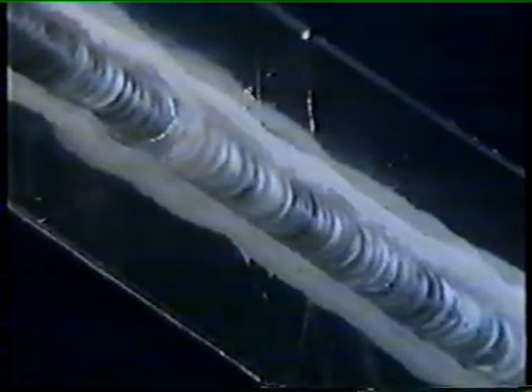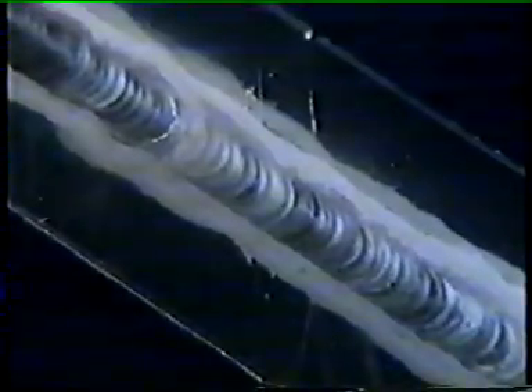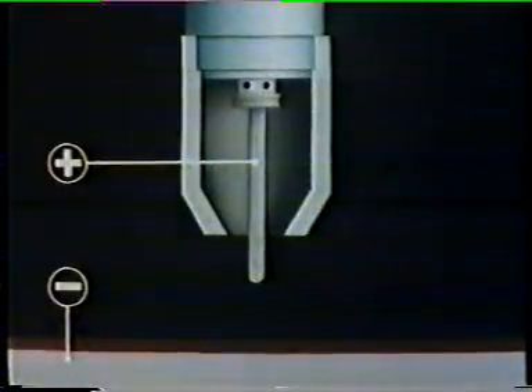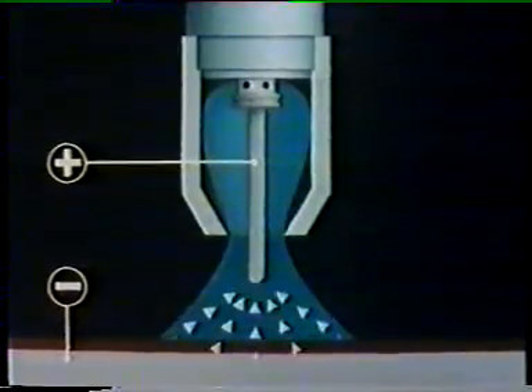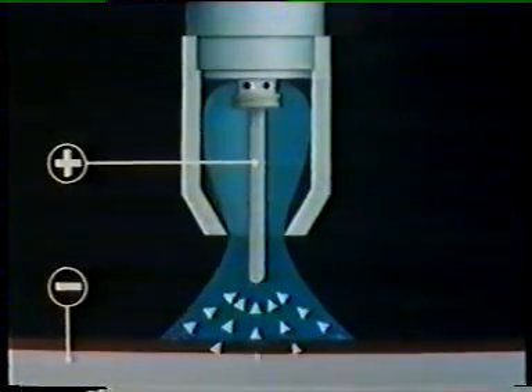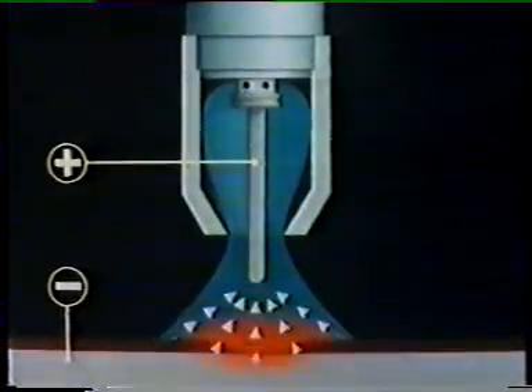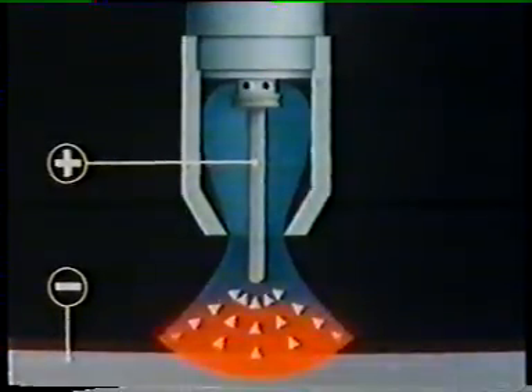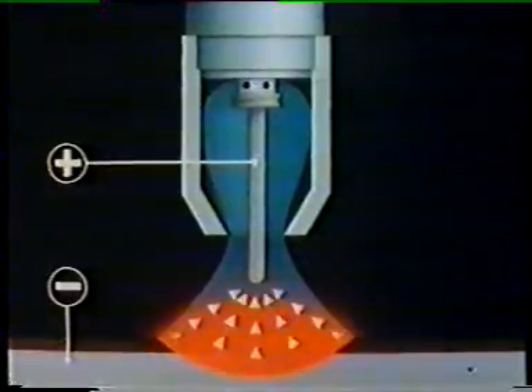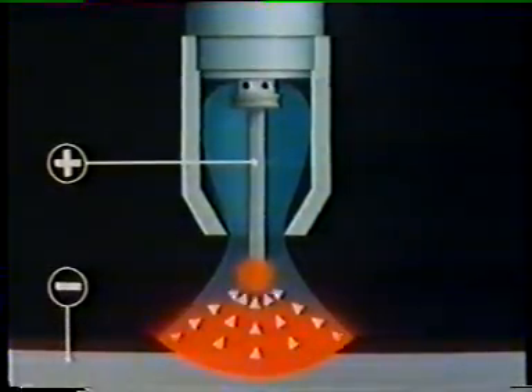Aluminium and its alloys present a major problem. When the parent metal is melted, the oxide skin is still intact, as its melting point is appreciably higher than the aluminium. As there's no flux in TIG, the oxide skin must be dispersed by the action of the arc. This happens only when the electric current flow is from the weld pool. That is, when it's negative and the electrode is positive. Under these conditions, oxide-free welds can be produced in aluminium. The main drawback is overheating of the electrode, which could eventually cause it to melt.